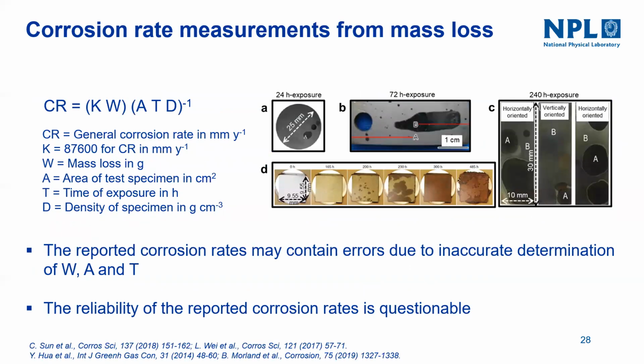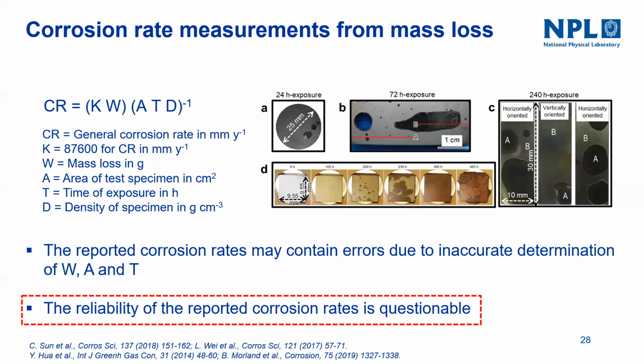So just to give a clear view, this is a general corrosion rate measurement. It has contributions from the mass loss, the area of test specimens, and the test duration. From the previous understanding, we have mass loss from water splashing and accidental condensation of water on the surface during depressurization. Also the time is not accurate, it's more than the actual time, and so is the area of corrosion. You can see that the area of corrosion is significantly lower, and in some cases significantly higher, but normally the whole area of the test specimens is taken into consideration. So the reliability of the reported corrosion rates is questionable.